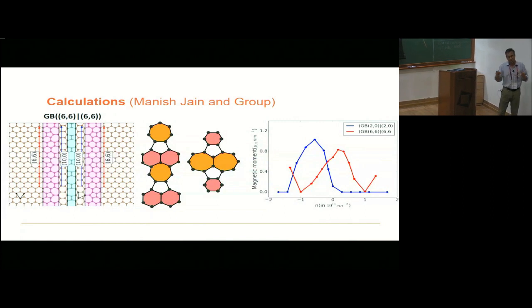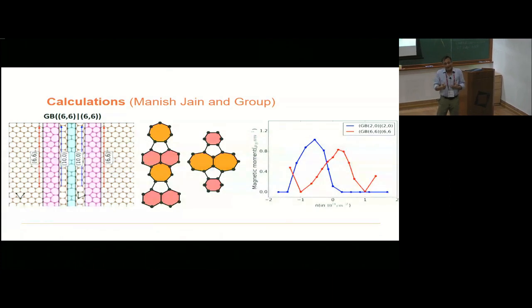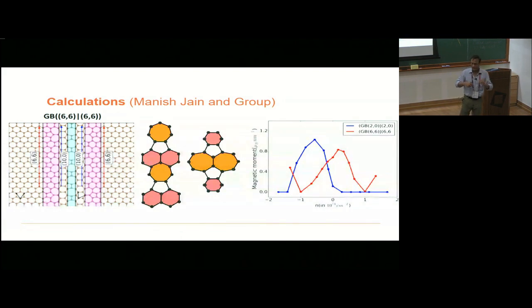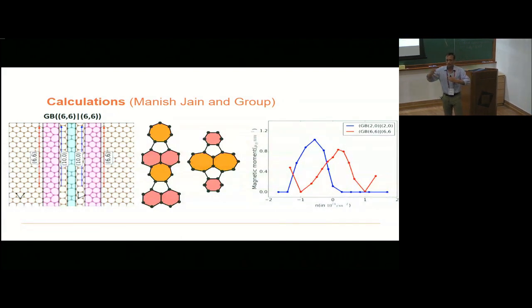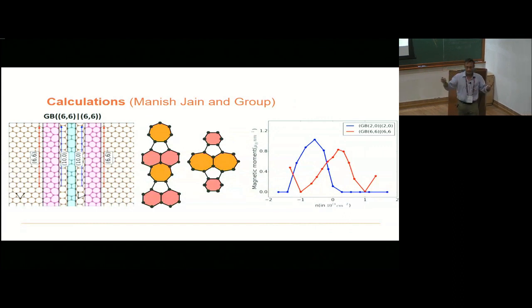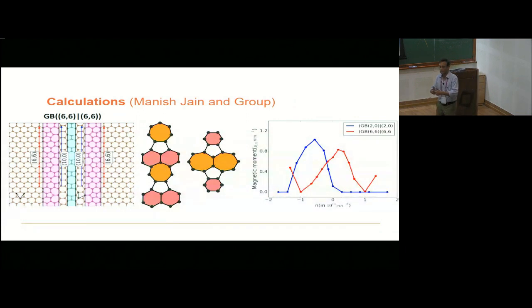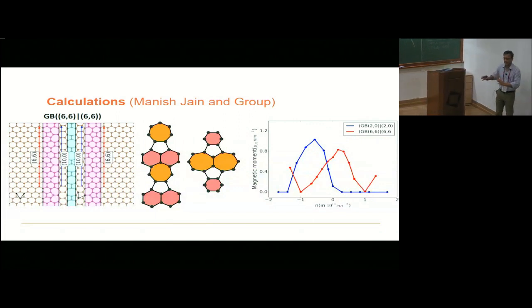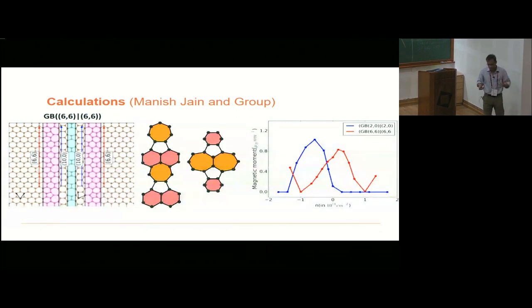A question, of course, remains whether these defects are indeed magnetic, or whether the fact that the time reversal symmetry seems to be breaking down as you increase the charge density in the system probably means that there are moments which can be communicating with each other through either RKKY interaction or something else, leading to some form of frozen magnetism, because breaking of time reversal symmetry requires frozen magnetism of some form as one possibility. But in any case, this is an open problem, and we are still trying to understand where the time reversal symmetry breaking can come from.